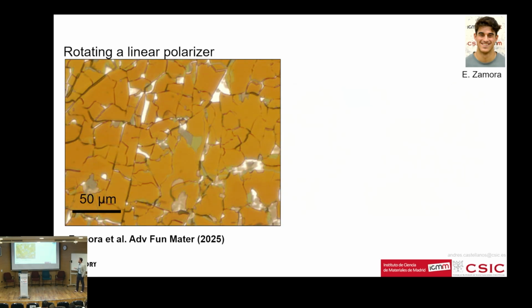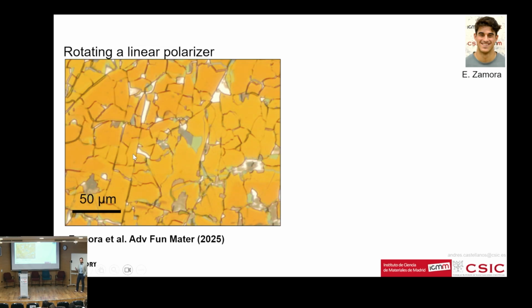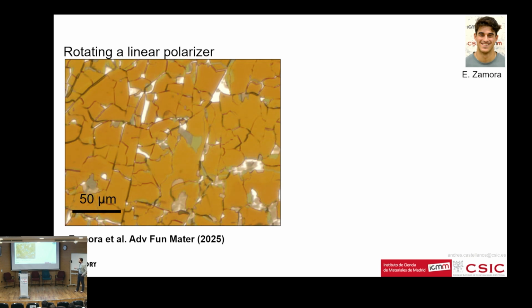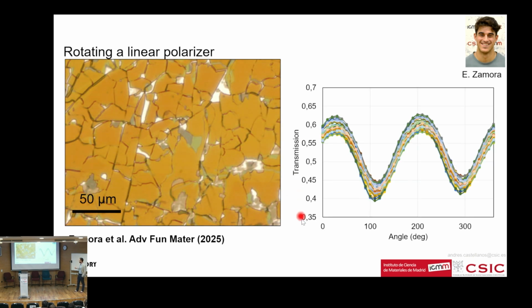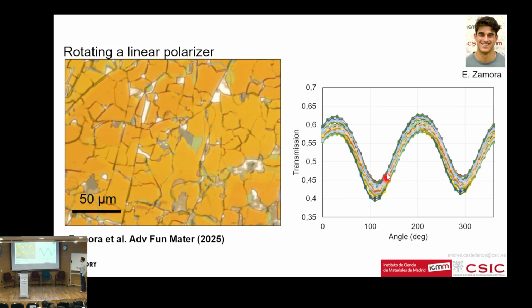And you can easily see that by making transmittance optical images with a linear polarizer that is being rotated. So basically you're doing linear dichroism, and you see how all the flakes change color at the same time. If you plot the transmission as a function of the angle of this linear polarizer, you see that indeed all the flakes have the same periodicity, without a big shift between them, okay?